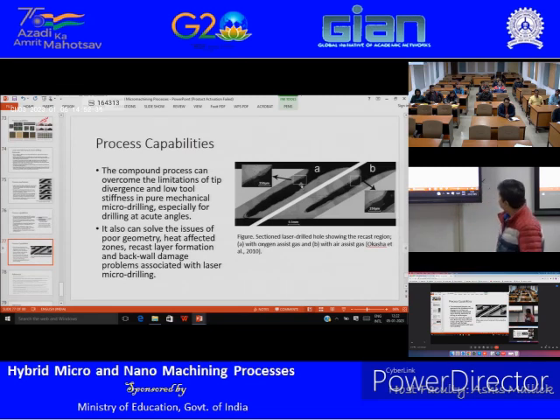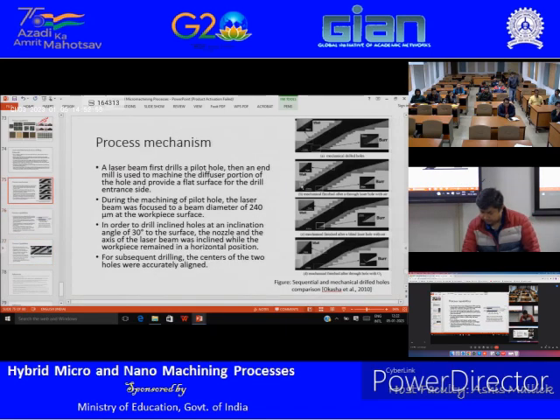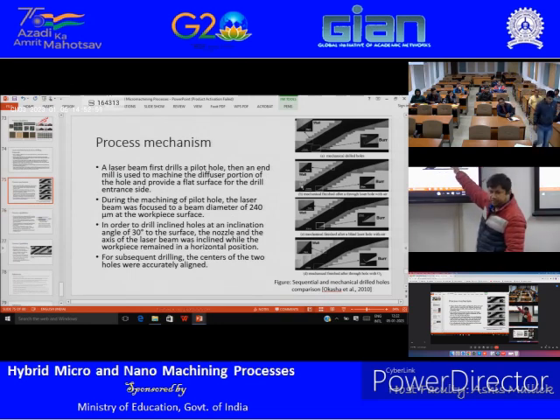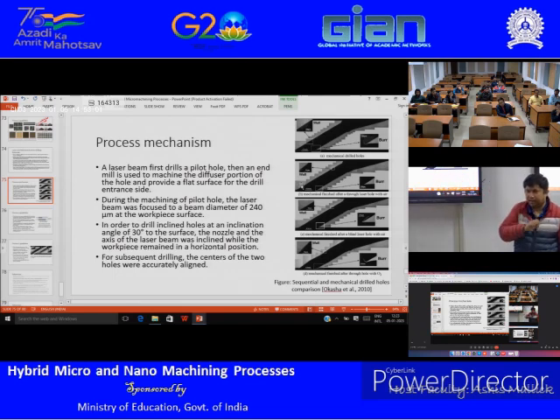Now here it shows some heat affected zone. It is a section of the laser drilled holes. The first one, A, shows lots of recast layer. And B, with air, also shows lots of recast layer. Then if you look at the previous one here, after mechanical machining, there is no recast layer, right? All the holes have smooth and sharp edges. So this is the sequential process.